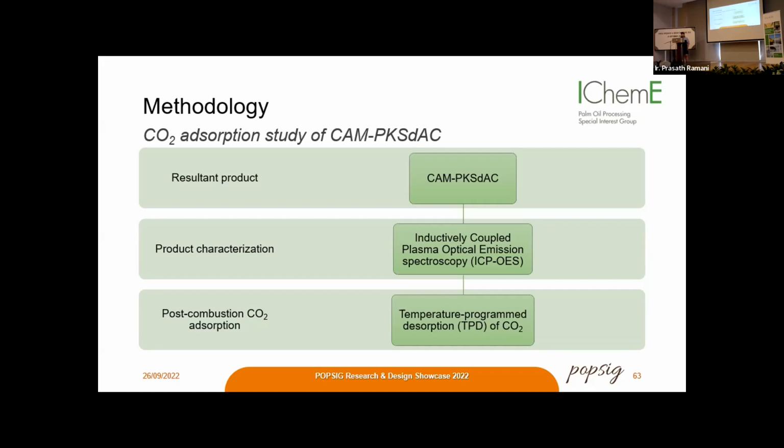ICP-OES is performed to determine the amount of present elements in the AC. This analysis is to make sure the metal salt incorporation is done on the AC, which will be responsible for the chemical adsorption of CO2. The CO2 adsorption performance of the AC will be tested using TPD, temperature programmed desorption testing.